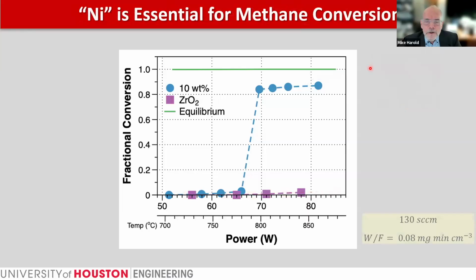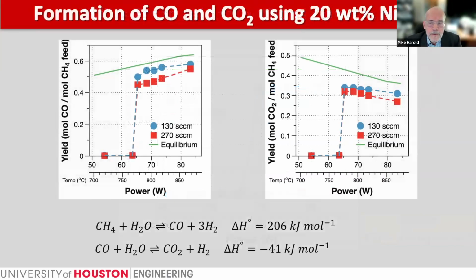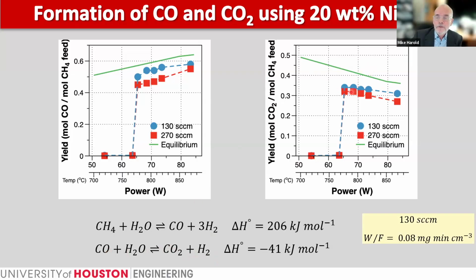So we compared the nickel zirconia to a nickel-free zirconia to check for sure that the nickel is the source of the activity. And indeed, this is the zirconia without nickel, showing very low activity at higher temperature. The measured CO and CO2 per mole of methane fed is shown on the left and right, and you can see that the results follow quite nicely the predicted equilibrium distribution of CO and CO2. What's kicking in at higher temperature is the reverse water-gas shift reaction, where produced hydrogen is reacting to push the CO2 back to CO. And that's why we get a maximum in the CO2 yield and an increasing CO yield with increasing temperature.